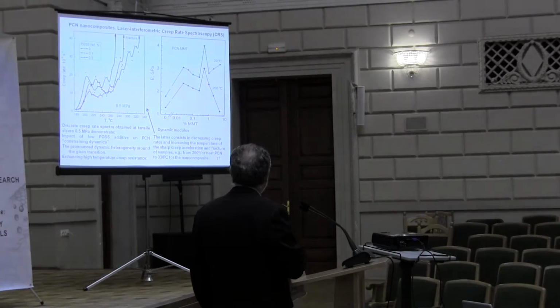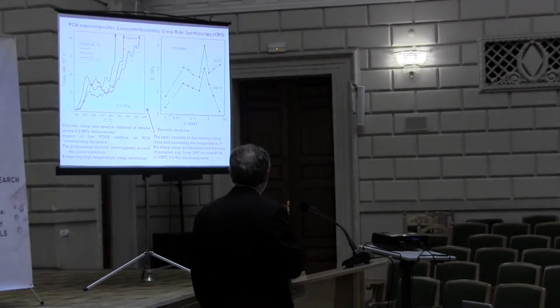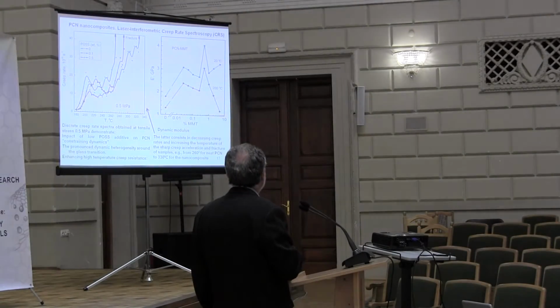And also polycyanurate nanocomposites were studied by laser interferometric Creep Rate Spectroscopy (CRS). And we fixed the impact of the low-cost additive on polycyanurate constraint dynamics. They pronounce dynamic heterogeneity around the glass transition and enhance the high-temperature creep resistance. So the effect consists in decreasing creep rates and increasing the temperature of the sharp creep acceleration from 260 for net polycyanurate to 330 for the nanocomposite. It's a 70 degrees increase, a very good effect.